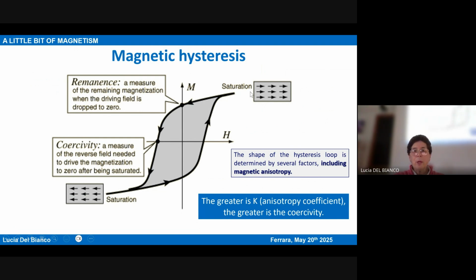So the shape of this loop, which means the saturating field, the value of the remanence, the value of the coercivity, is determined by many, many different factors. But an important factor is magnetic anisotropy. And therefore, please try to remember this sentence: the greater is K, the anisotropy coefficient, the greater is the coercivity. Okay?